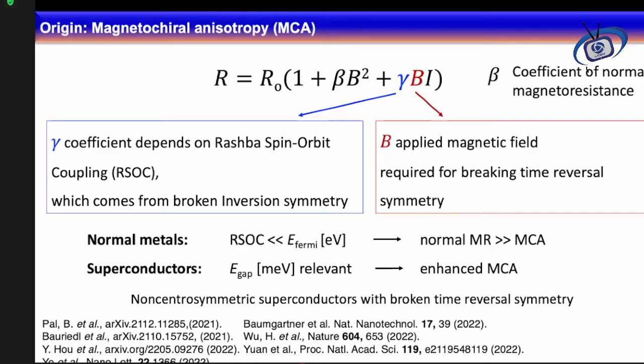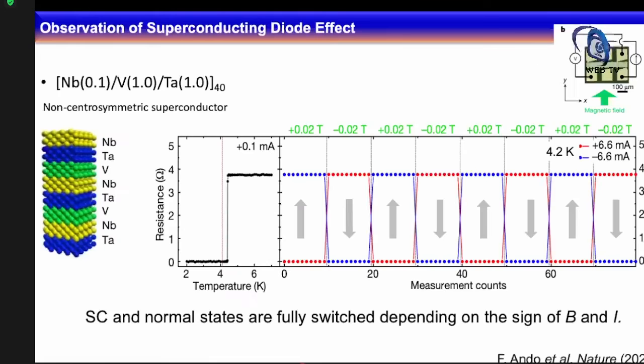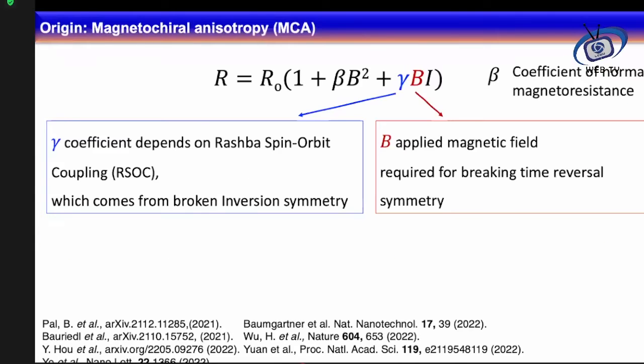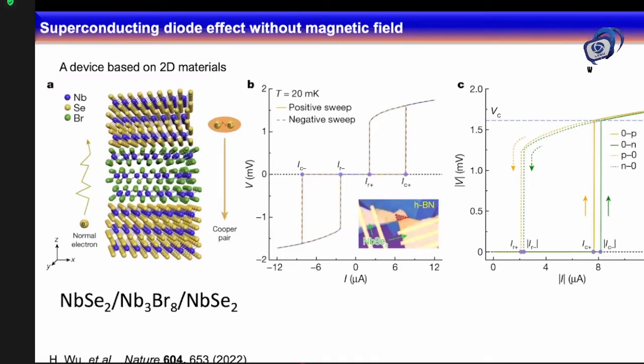Interestingly, there is a type of superconductivity that we call non-centrosymmetric superconductivity. By the name, you can understand that non-centrosymmetric means that the crystal has broken inversion symmetry. So it means that those superconductors intrinsically have very high spin orbit coupling. This structure which I showed you here is also a type of non-centrosymmetric superconductivity. However, these older superconductors, though they were used to develop this structure, are normal centrosymmetric superconductors.